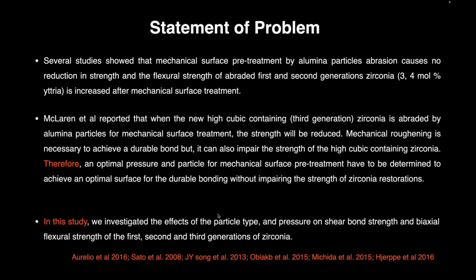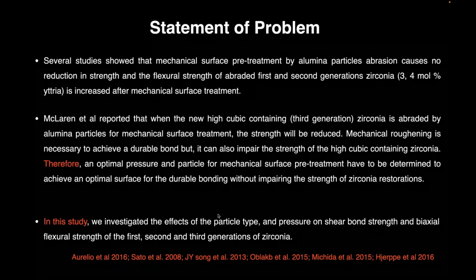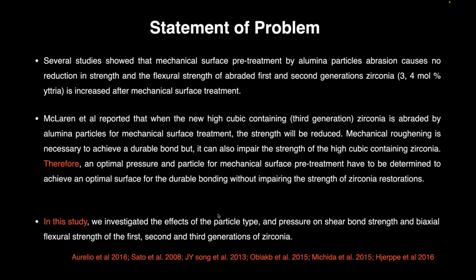Since zirconia has changed from strong zirconia into more translucent but weaker zirconia, McLaren and his group reported that when the new high cubic containing third generation of zirconia is abraded by alumina particles for mechanical surface treatment, the strength is reduced. The mechanical roughening is necessary to achieve a durable bond, but it can also impair the strength of the high cubic containing zirconia. Therefore, the optimal pressure and the particle for mechanical surface pretreatment have to be determined to achieve an optimal surface for durable bonding without impairing the strength of zirconia restorations.